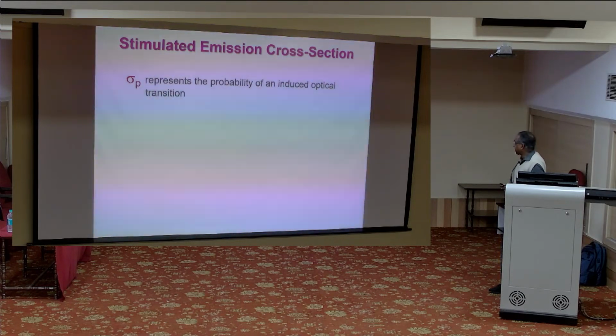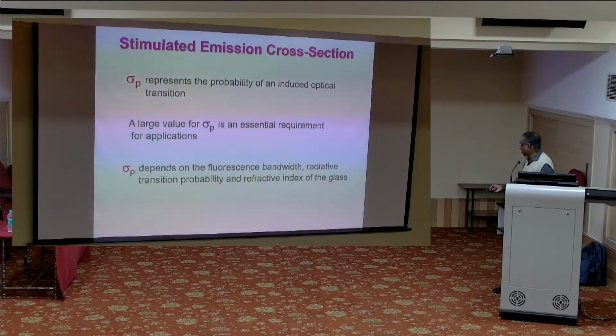So we look at this particular quantity, sigma p. Basically, it represents the probability of a stimulated emission transition: how easy or how hard it is for a samarium ion to emit after it gets excited. So that decides the intensity of the emitted light which is coming from that. If you want to have very good emission, it is preferable to have a larger sigma p value. That's an essential requirement for our practical applications. This depends on the bandwidth, the width of that particular line, the radiative transition probability, another quantity that we calculate from optical absorption, and the refractive index of the glass.